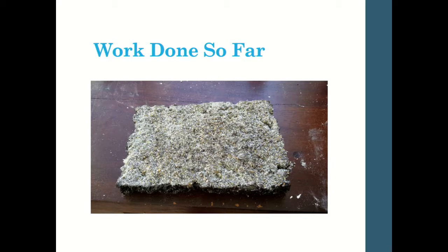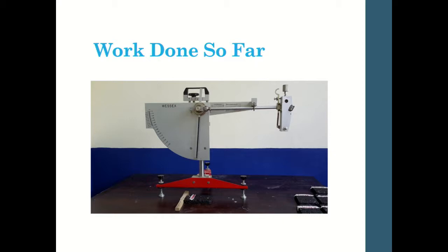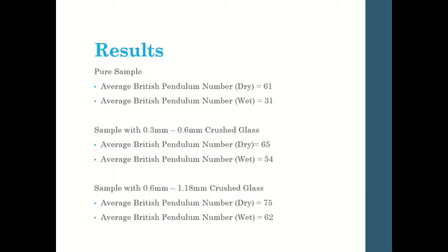Now, to test the skid resistance of the surface, I use a British pendulum. What happens is that you have this pendulum attached with a rubber bit at the end, which swings and brushes the surface of the sample and reads off a number along here that will tell me how much friction this surface has. So what I've received so far, based on my preliminary tests, was a number of 61 for a dry, pure sample, and a number of 31 for wet. The reason I have to do this under both dry and wet conditions is that skid resistance is affected by moisture. Whenever you're having that issue of skidding, it's normally when the surface is wet rather than dry.